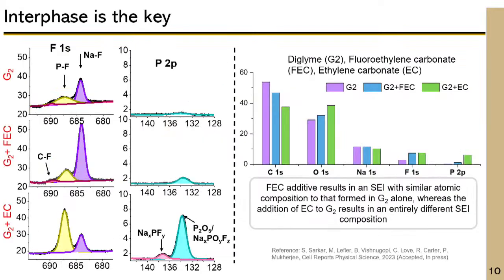Now I wanted to look into what's going on at the interface. I won't bore you with the details of this analysis, but this is the XPS analysis. In summary, what we see is that when you have ethylene carbonate added in the electrolyte, it promotes dissociation of your electrolyte salt. In an electrolyte, you have a salt and a solvent - you don't want too much dissociation of your salt. From the interfacial analysis, we see too much dissociation of salt when you have ethylene carbonate, but with fluoroethylene carbonate it was not there. It was able to form a very good, optimal layer, which allowed uniform charging and discharging.